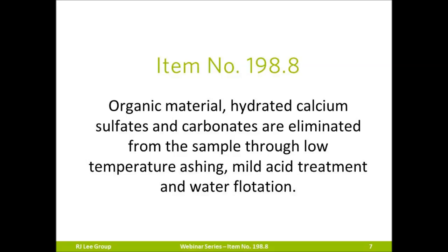Spray-on fireproofing contains several constituents that interfere with PLM analysis for chrysotile. Both the Lab 055.1 and the 198.8 methods remove cellulose, paper fibers, gypsum, hydrated calcium sulfate, and carbonate by low-temperature ashing, water washing, and mild acid treatment.